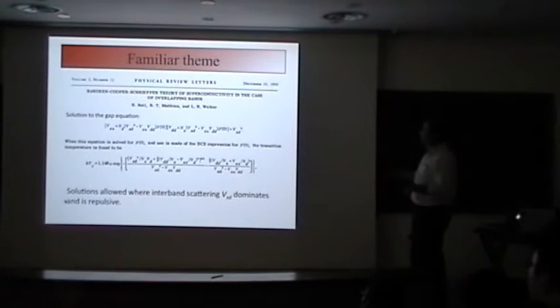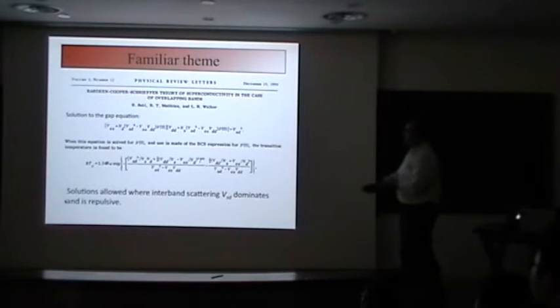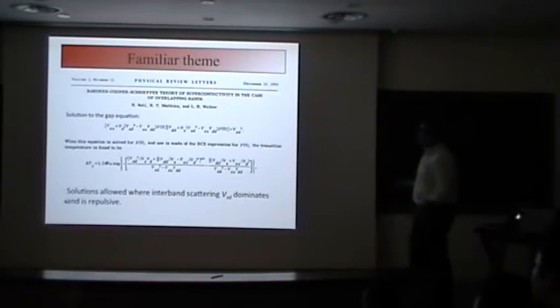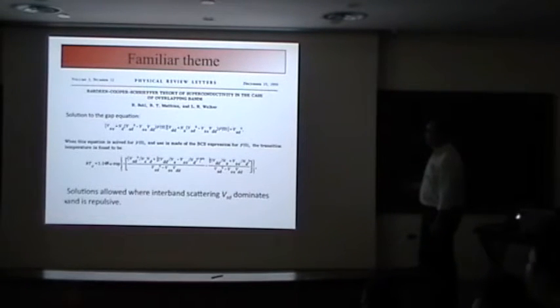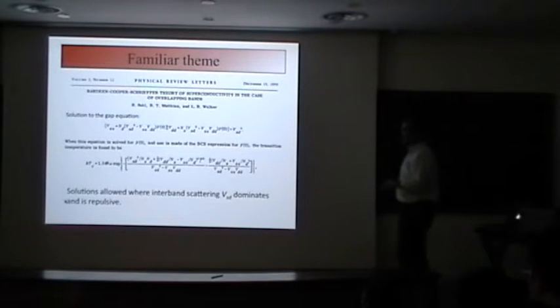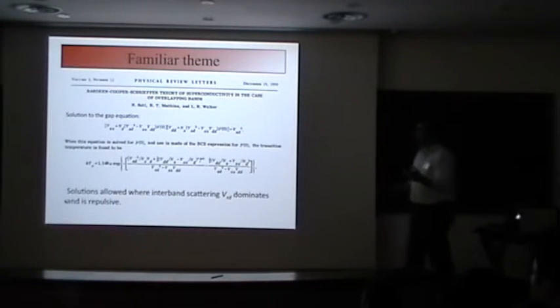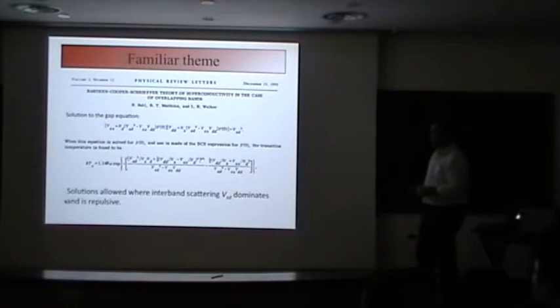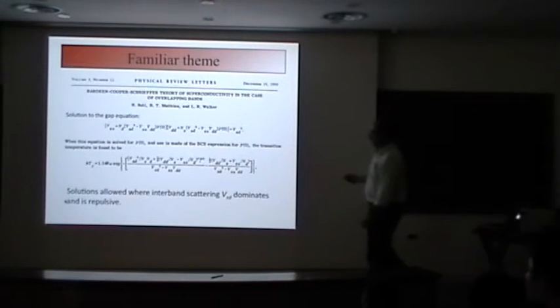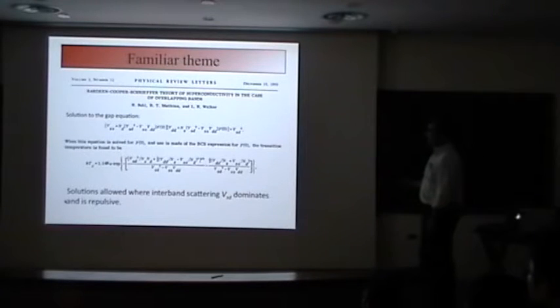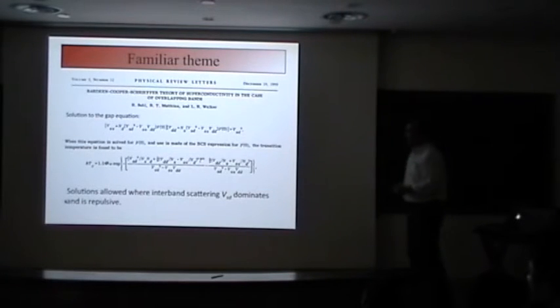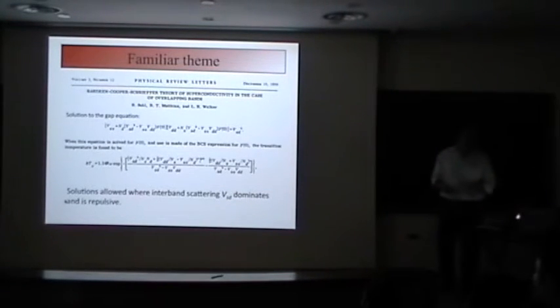This is a good idea, but it really stems back to the work of Harry Suhl, who looked back in 1959 at the idea of having superconductivity in a multiband system. Here's his equation for Tc in terms of intra-band scattering, say VDD or VSS for the two bands, and interband scattering, VSD. If you switch off that interband scattering, the only solution you get for an S-wave superconductor is to have these V's be negative. But if you turn off VSS and VDD, this is a simple exercise to see, you also get a solution to this equation. So you can get a pairing where the solutions are allowed predominantly because of the interband scattering being repulsive.